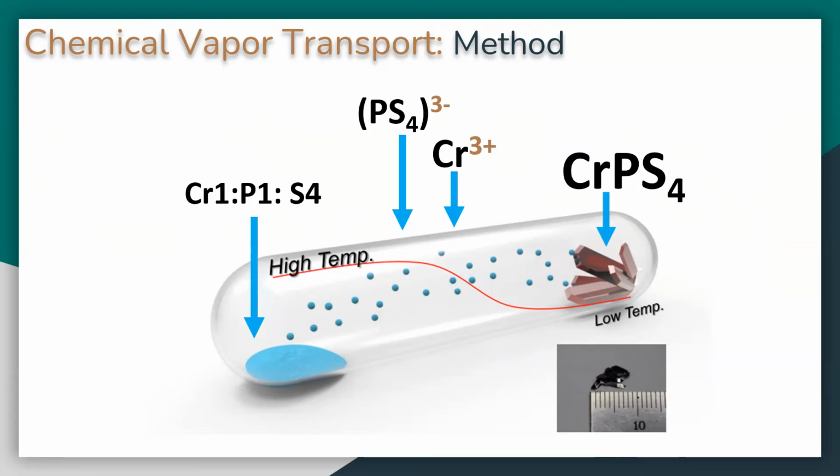The temperature gradient through the ampule is warmed up in a special furnace called a 3-zone furnace. And then the sample is inserted into the ampule. The process is exothermic and is quick to happen for chromium thiophosphate, and you can actually see the vapors almost immediately during that process. So after a few days, the furnace is turned off and the sample is cooled with the furnace. The purest chromium thiophosphate sample is collected at the zone around 710 degrees, and at the 750 degree zone, chromium 3 sulfide powder is found along with some slag.